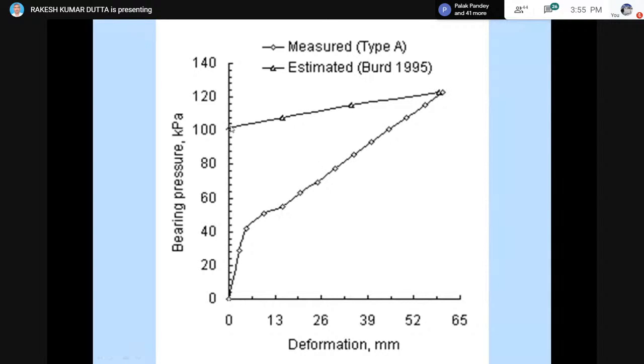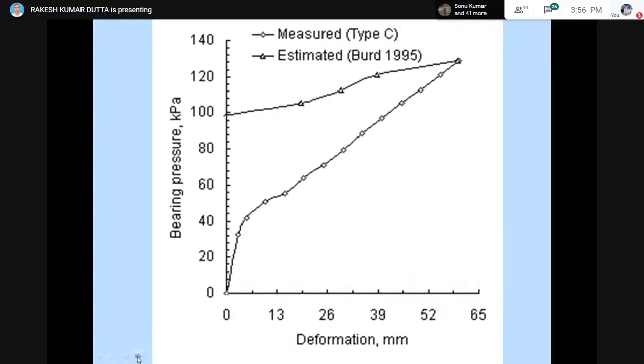Here in the initial part of the study, you see the stiffness predicted by Burd's 1995 model is much higher, whereas the prediction improves at larger deformation. At this deformation, both curves are approaching each other. That means Burd's model overestimates the stiffness of the model which we have taken for the study in the beginning. This is the limitation of Burd's model. This is with type A. A similar conclusion was drawn using a type C material.